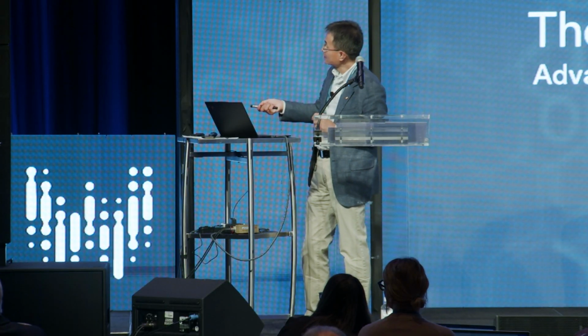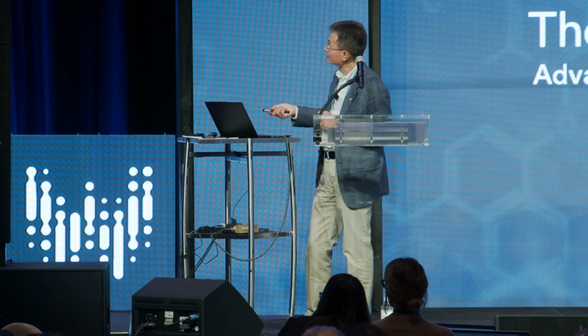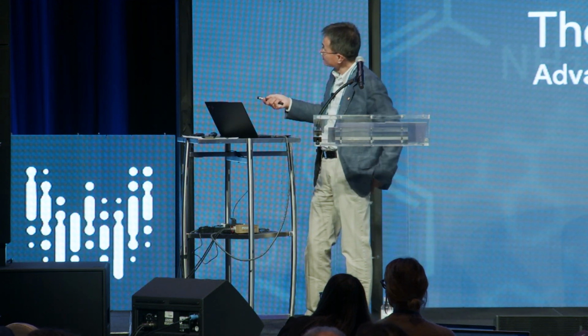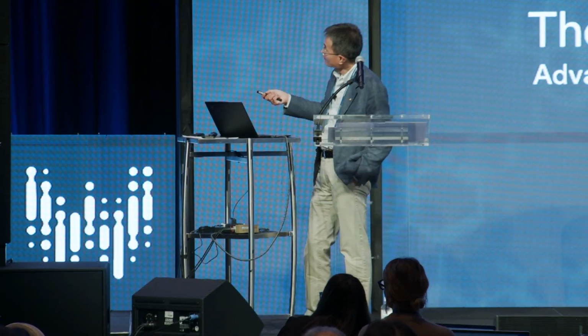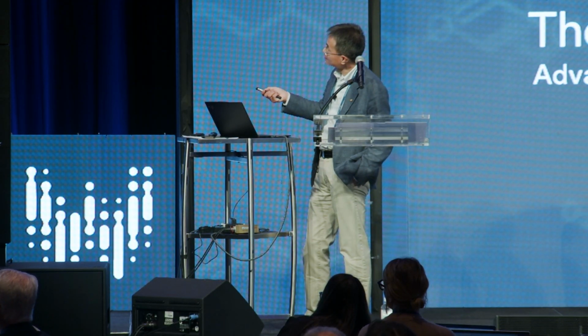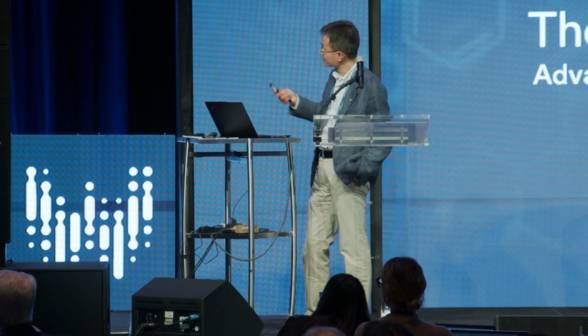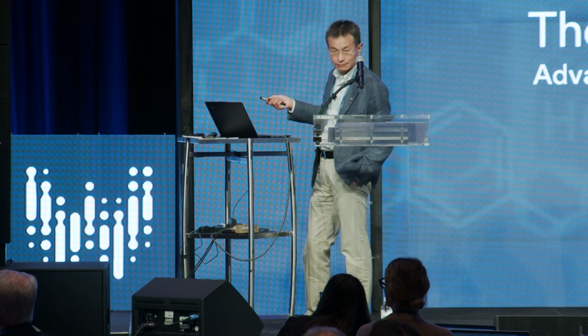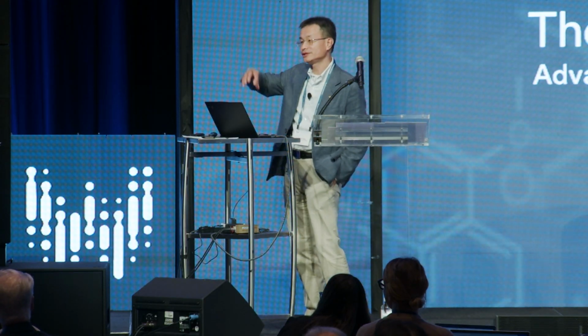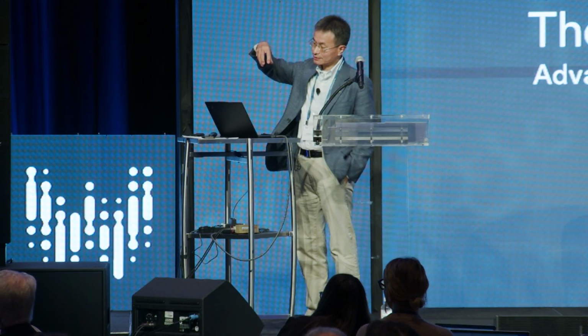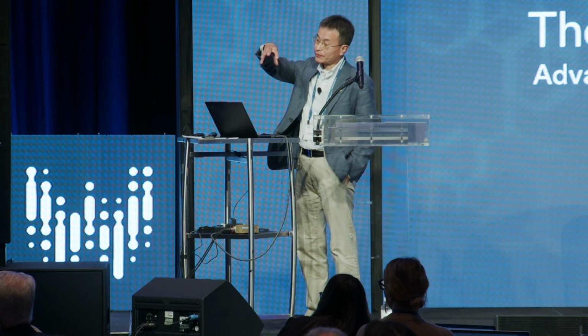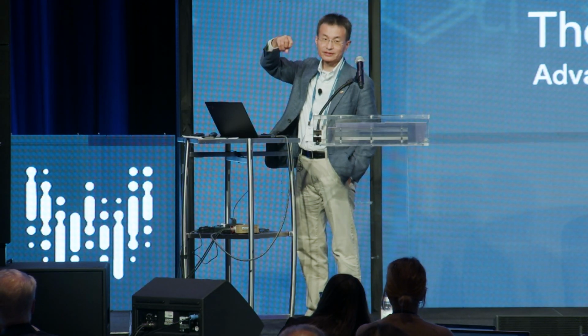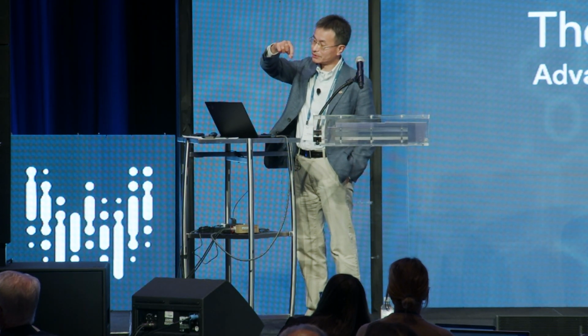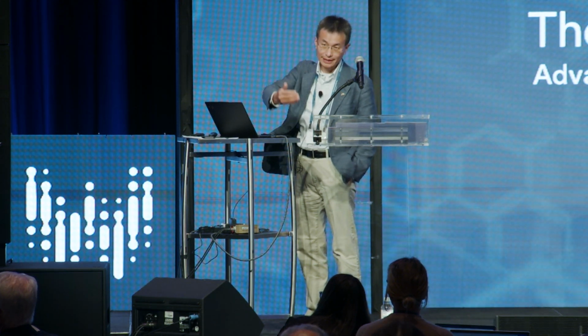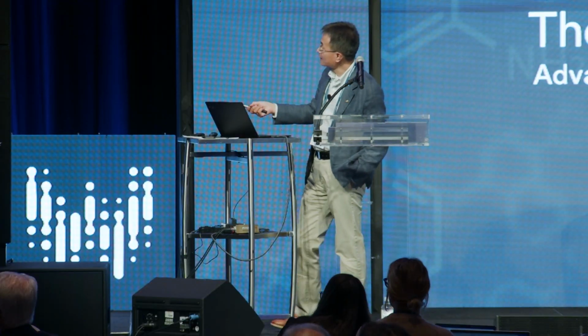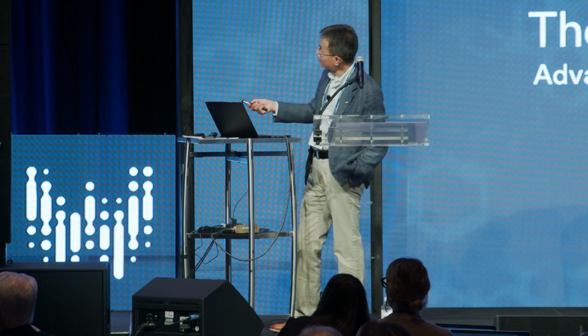That's my first graduate student, Yiying Wu, now at Ohio State University. This work we carried out in the in situ TEM, in the Molecular Foundry, whose older name is NCEM, at very high temperature, 800 degrees in the TEM column. During this stage, what we're doing is sprinkling the TEM grid with gold nanoparticles of different sizes. Then, with the neighboring material, you generate germanium vapor by heating the grid, and that essentially generates germanium vapor locally around the gold nanoparticles.